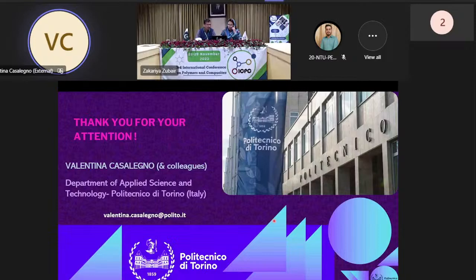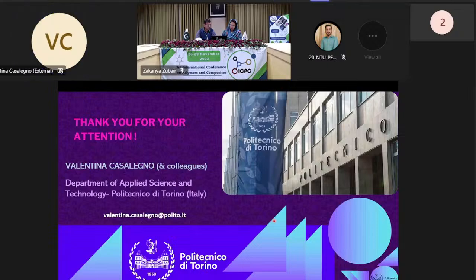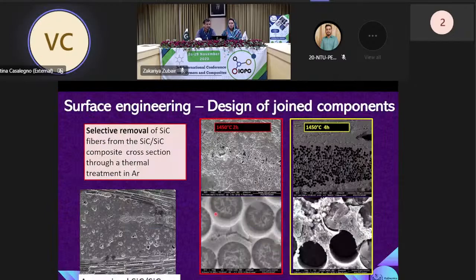The idea is to put the samples of composites in a furnace, and using a treatment at high temperature for different times, try to have a sort of preferential etching of the fibers that are different in terms of crystalline phases, even if the chemical composition is the same, since the matrix is silicon carbide, but also the fibers are silicon carbide, but they have different crystalline structure. And so we can obtain a sort of corrosion of the fibers, starting from the top of the surface.